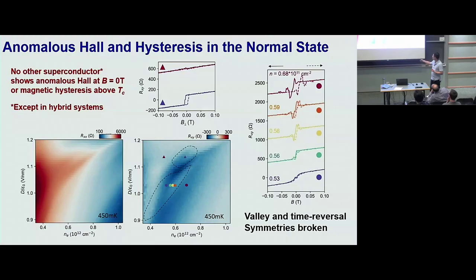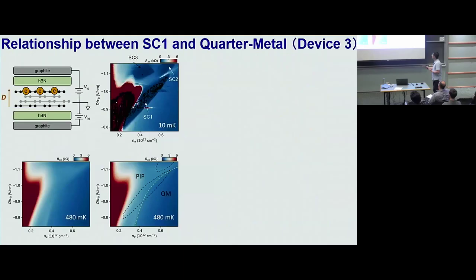These dashed ovals here outline SC1 and SC2, okay? And if you park inside there, SC2, you do hysteresis, you got a loop. You got anomalous Hall resistance, you got the magnetic hysteresis loop in both the SC2 region and the SC1 region. There's clearly anomalous Hall and hysteresis. So valley and time reversal symmetry are broken at the orbital level before you get into the superconductor. Okay, a little bit more.